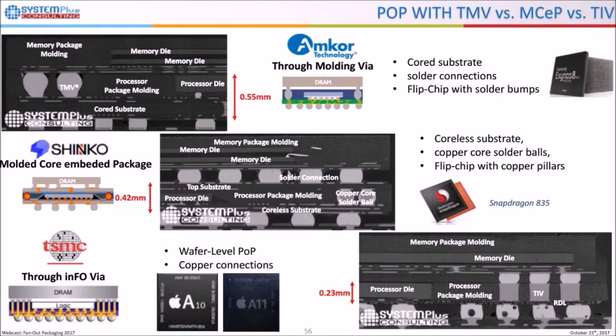and increase the electrical performance. And now TSMC proposed the InFO packaging with through InFO via, represented by copper pillar around the AP. The benefit is that copper is a very good material for electrical connection, and also it doesn't require a PCB substrate here because the process uses RDL. So it's a relatively cost-effective packaging